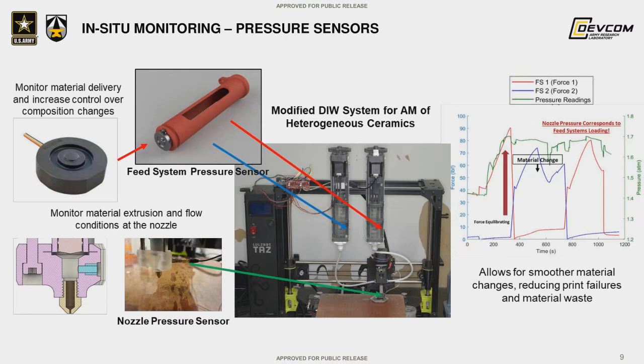More recently, we've also been doing a lot of work on in situ monitoring via pressure sensors of the pressures in the plungers, which has enabled us to allow for smoother material changes, reduce the print failures and material waste, and generally given us the ability to print more reliably and with fewer defects from nozzle clogging and other issues that we typically run into when running this system.